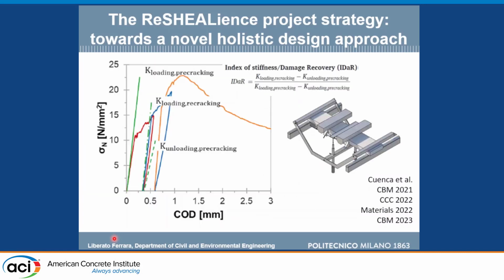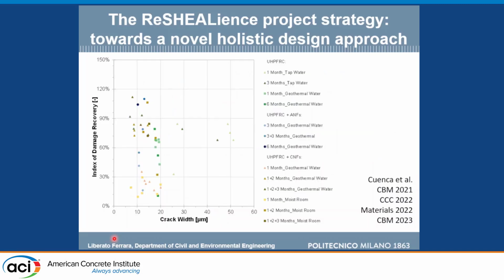This was not only on the closure of the cracks, we could also see on the capacity to recover the damage. We intended the capacity to recover the stiffness, the flexural stiffness that we evaluated from this cracking and re-cracking test. And you can see here that the mix with alumina is here, and the mix with nanocellulose are the yellow ones, where the reference is here with less performance and wider cracks.